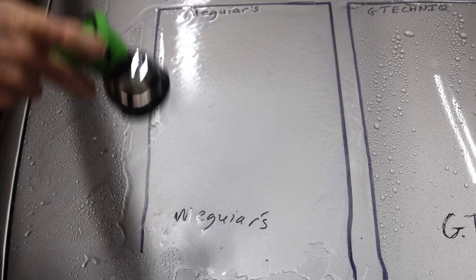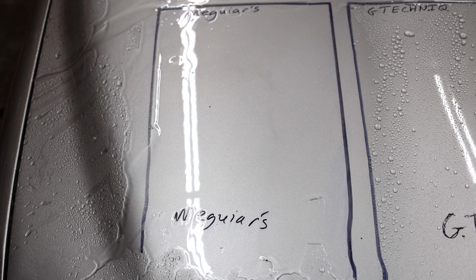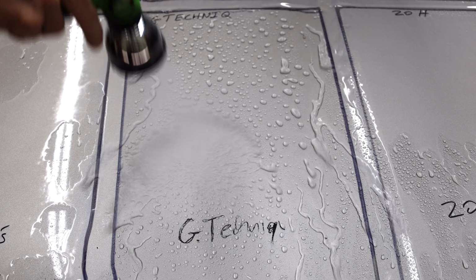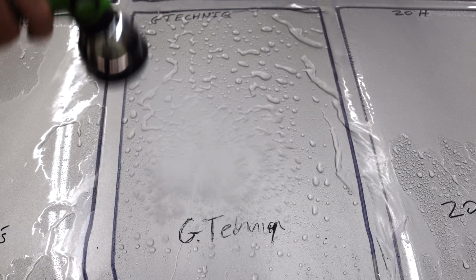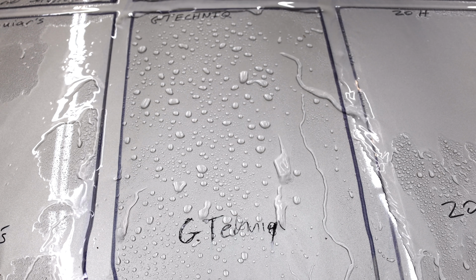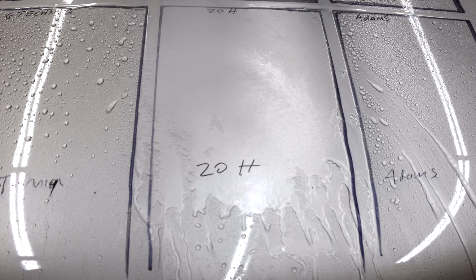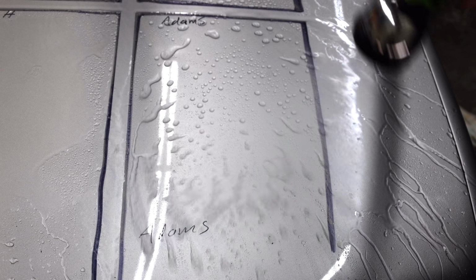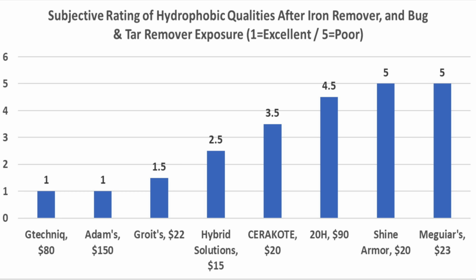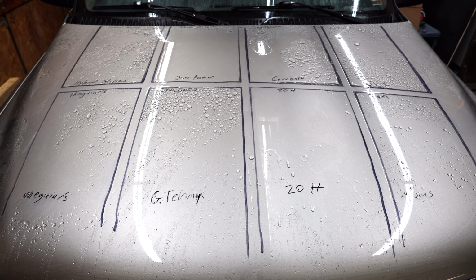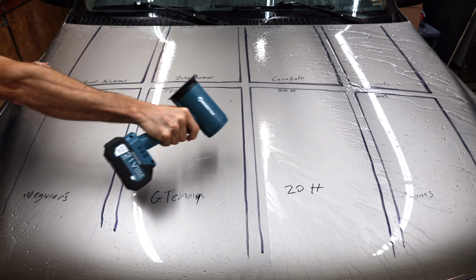Bug and tar remover is a powerful product and it's completely wiped out the Meguiars. And the bug and tar remover didn't stand a chance against the Gtechniq and it still looks as good as new. Very impressive. The 20H is really struggling compared to the Gtechniq. Just like the Gtechniq, the Adams coating shrugged off the bug and tar remover without a second thought. Very impressive. So the Gtechniq and Adams are still looking as good as new with the best possible rating of 1. The very affordable Griot coating isn't too far behind with a rating of 1.5.